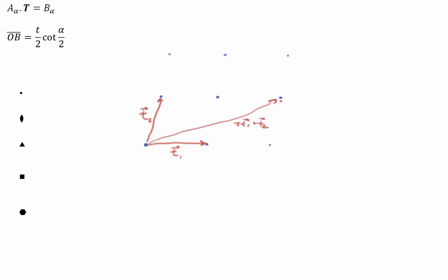So in the absence of any rotation axes or any mirror planes of symmetry, the most general two-dimensional lattice type that we can have is composed of parallelograms. This shape right here is a parallelogram. And just as a reminder, that means we have two pairs of parallel lines. There's a pair of parallel sides here and a pair of parallel sides here. There's no restriction on these angles. So this is the first kind of plane lattice we can have, a parallelogram.